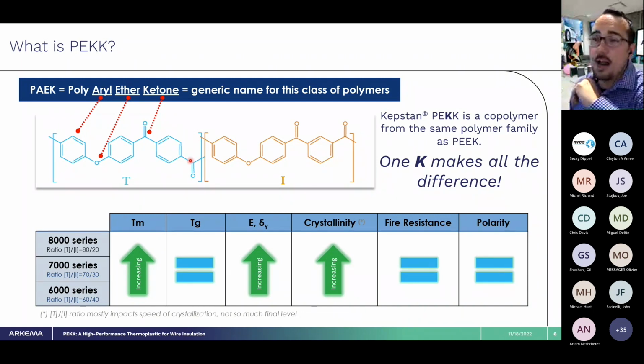So you have your meta and your para position, or what we call terephthalic or isophthalic structures. By creating essentially a copolymer of these, we can tune the crystallization kinetics, the chemistry, and the final properties of this material to be applicable to a variety of processing conditions, and also tune the end properties. So what we do is create a ratio or copolymer of these two.